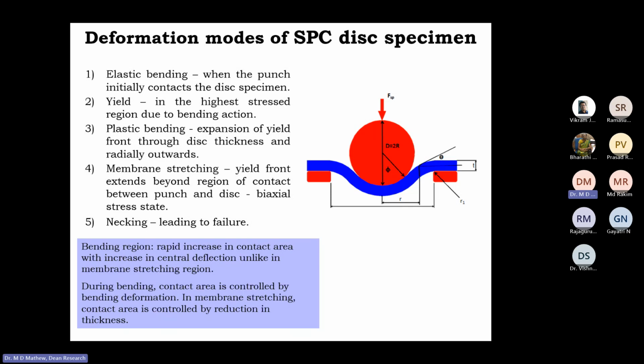Let me add 2 points. One is, even when we do a hardness test, there is a relationship depending upon the diameter of the indenter and the thickness. If you are using a large diameter, your material has to be thicker, right? I think there's a ratio of some 1:3. The sample thickness should be more than 3 times the depth. So likewise, in this case, you can have a small sample, but it depends upon how much you want to penetrate.